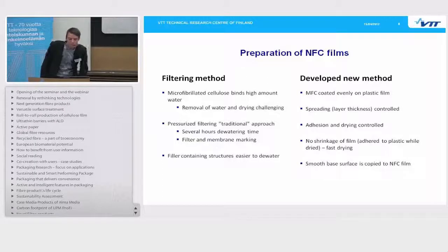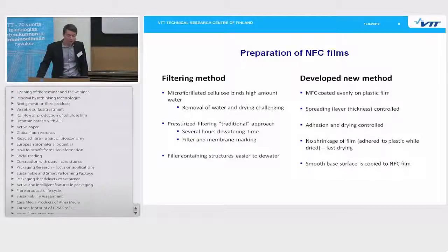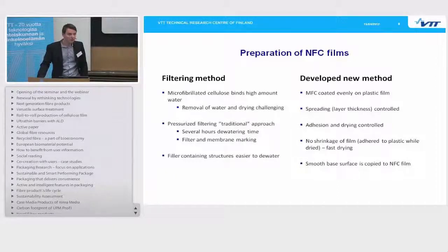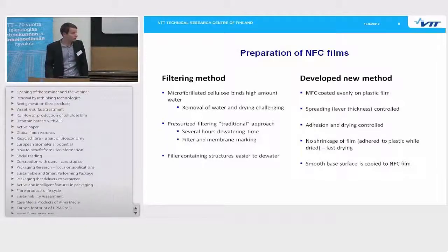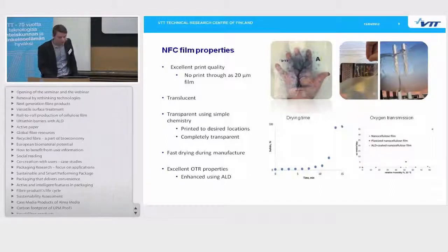What we have done is coat nanocellulose or microfibrillated cellulose evenly on a plastic support. We can control the layer thickness of the film as we wish. During drying, we also control the adhesion and drying conditions. By controlling the adhesion to our plastic support, the nanocellulose film does not shrink during drying — meaning there will be no wrinkles in the finished film. Also, the smooth surface of the plastic support is copied onto the NFC film, so there is no problem of filter marking.